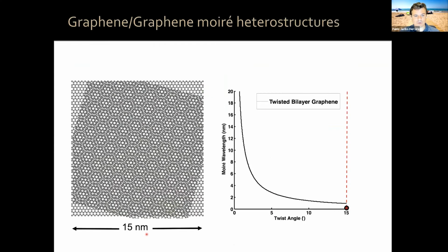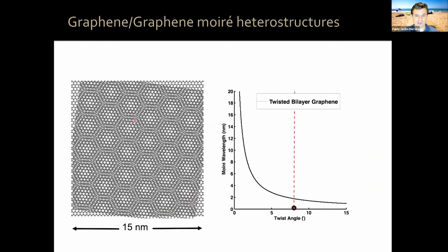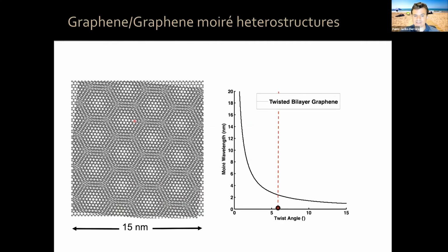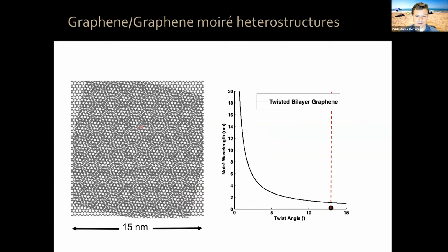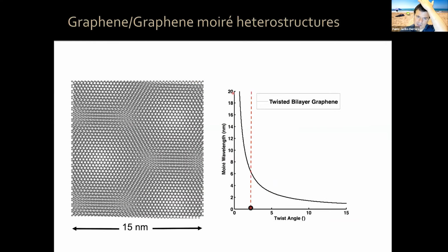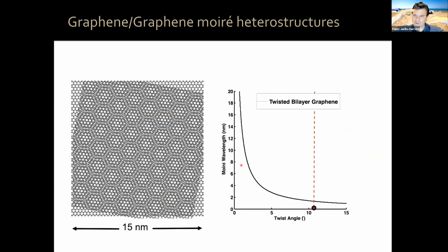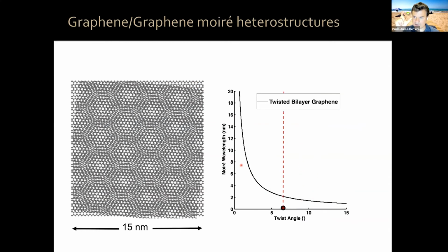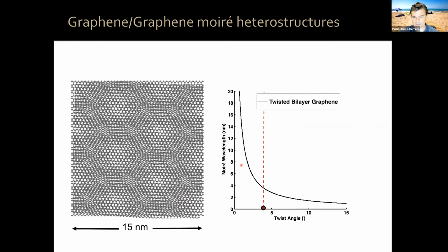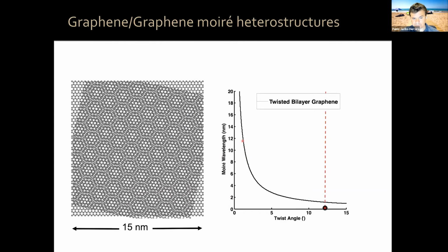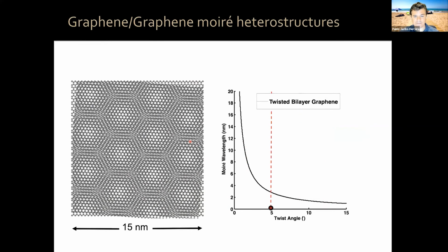Now, what happens if you put graphene on top of graphene and you rotate the angle? A Moire pattern forms, where the Moire wavelength, the distance between the soccer balls that you see on the screen, is roughly inversely proportional to the twist angle. So you form a super periodic structure which has this Moire pattern with a very long wavelength at small angles. Now, let me stop this before you get dizzy.